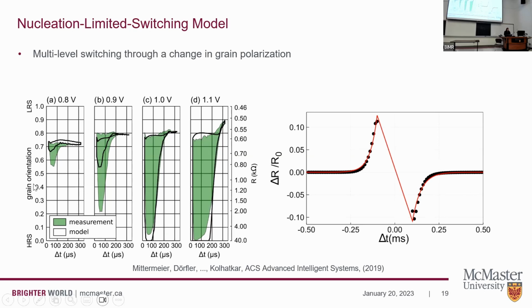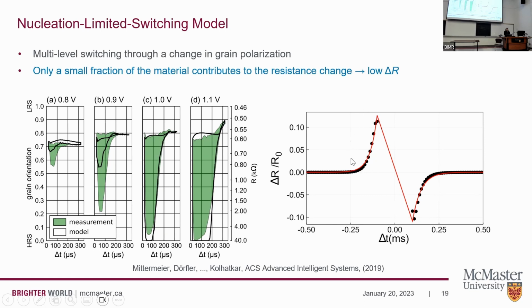So now when we look back here at the first curve, we can see that only a very, very small fraction of the grains is actually contributing to the switching. This leads to a very low change in resistance that we observe here, that is only about 0.1, which is significantly lower than what we would expect in our brain.